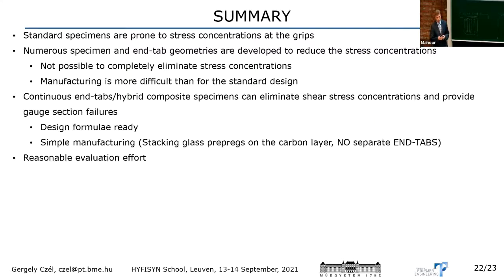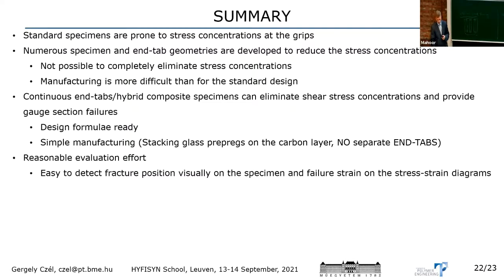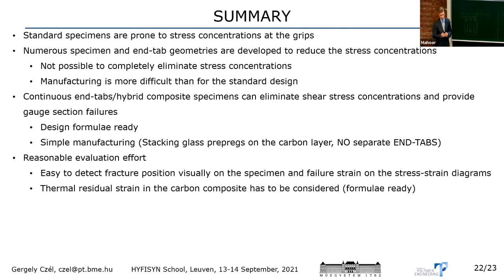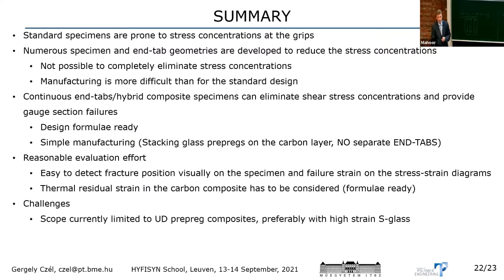Few points about design. So we have our formulae ready for designing the hybrid specimens, and at least to my judgment, it's not complicated to make them, not worse than making a standard specimen, and the evaluation effort is also reasonable. It's easy to detect the failure strain on the test graphs, and also the thermal residual strain correction can be done with reasonable effort. Okay, it's a complication, but can be handled. But there are still some challenges.